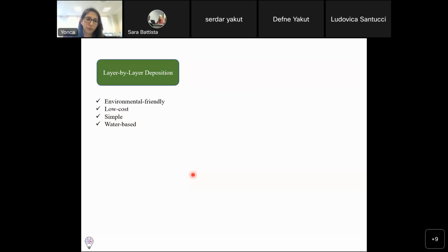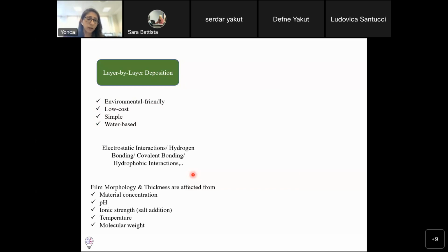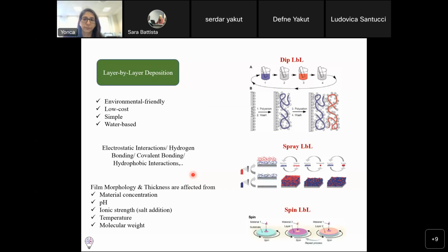So as I said, it's water-based. Mainly the interactions are electrostatic, but you can have molecular interactions like hydrogen bonding and covalent bonding, so it's not only limited to that. In order to have control over thin film morphology and thickness, you need to check certain parameters: the material concentration, pH, ionic strength, in some cases temperature, and the molecular weight. These are the parameters that highly influence the overall thin film properties.